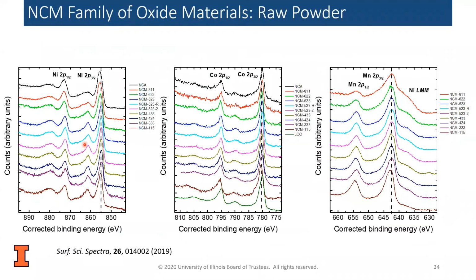So let's start with some characterization of the batteries. This is the NCM family of the raw powders. We can actually gain a lot of insight in terms of the aging characteristics of the battery just by looking at the raw powder. Because when the powder sits in its dry room, it's still going to be exposed to a little bit of moisture, and so it'll build up a hydroxide layer on the surface. What happens then is the lithium hydroxide can pull CO2 out of the air and form carbonates. That's pretty similar to what happens in an actual battery.